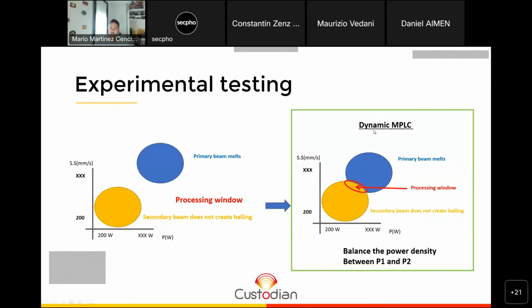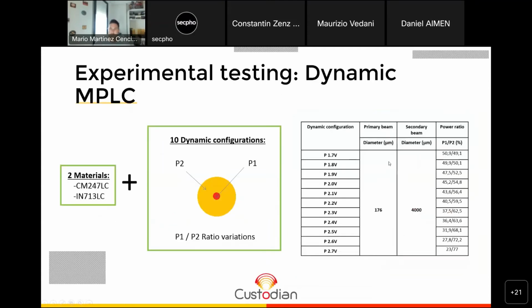So that's why the dynamic MPLC was focused on playing with the power ratio between the primary and the secondary beam. Again, a Gaussian distribution from the primary, top hat for the secondary, and we have this range of voltage that we can adjust in the piezoelectric, in the galvo mirrors, so that depending on this value, we can obtain a power distribution between the primary and secondary beam, as you can see on the table. We can play from 50-50 to 23-77 for the secondary beam.